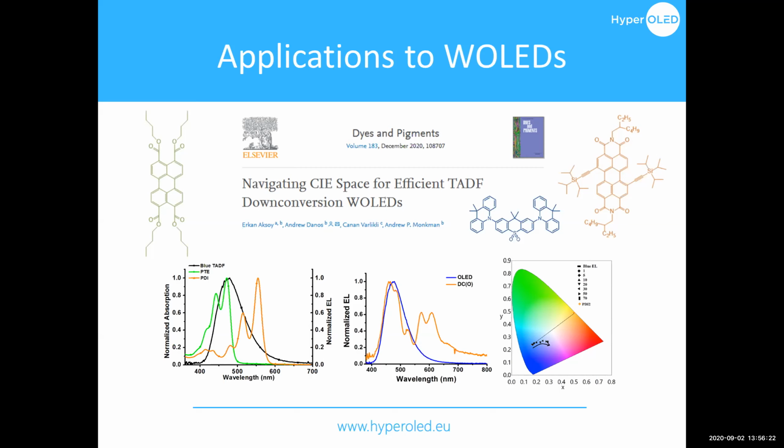And so when we did this, it required some very clever and slow and patient application of the orange down conversion layer to prevent the perylenes from aggregating. But when we did, we found that we actually got a nice blue peak, a nice orange peak, and a white coordinate that didn't really go where we expected it to. It went a little bit towards white, but as we got closer and closer, it curved away down into the bluey purpley region. And at first we had no real idea of why that was happening.